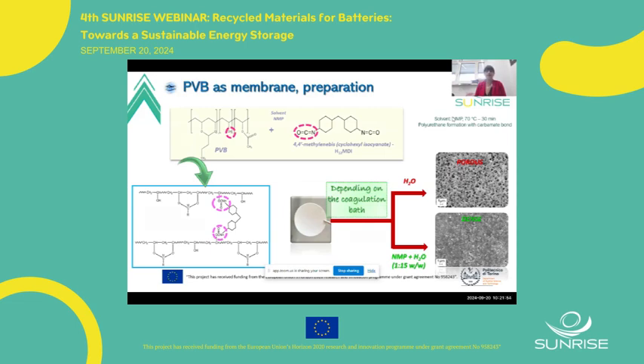Then we increase the temperature up to 70 degrees, and the solution is cast on glass with a doctor blade, followed by immersion in the coagulation bath. Depending on the coagulation bath, we achieved two different morphologies, porous and dense.